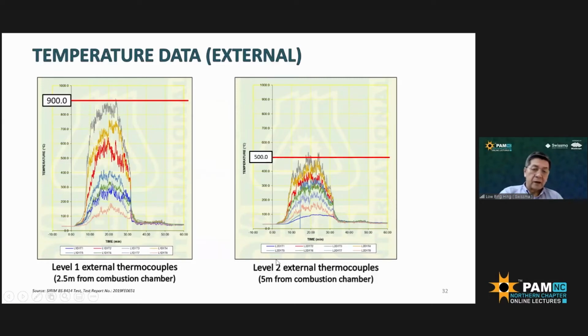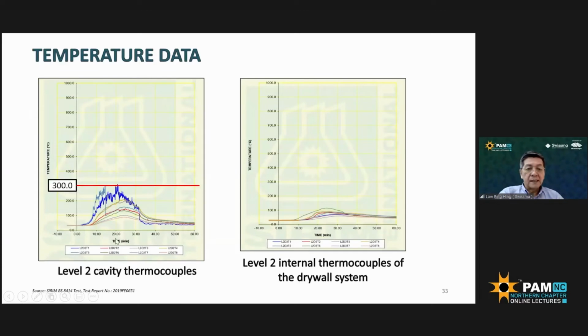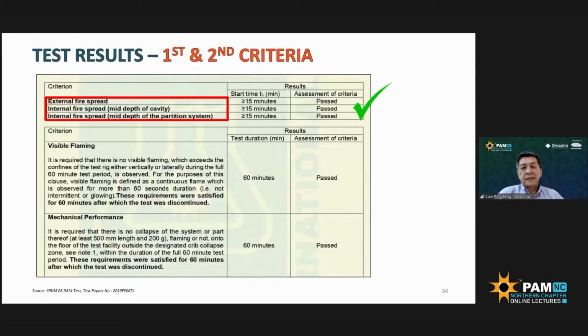You can see that on this timeline, the horizontal is the time and the vertical is the temperature. The intensity of the heat rises and subsides. This is the level two cavity thermocouple, which is in the cavity of the drywall. Here the test report stated very clearly that external fire spread and internal fire spread within the 15 minutes, all three pass.